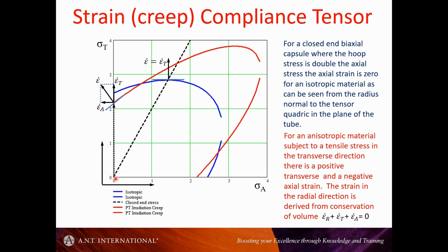And we do a uniaxial test and follow this stress locus where it intersects the yield surface. For a transverse tensile specimen, we see what the transverse strain rate is compared to the axial strain rate. Anyway, once you've figured out what F, G, and H apply to your material, whether it's isotropic or anisotropic or how it's anisotropic, then you can deduce how it's going to strain for a given stress.